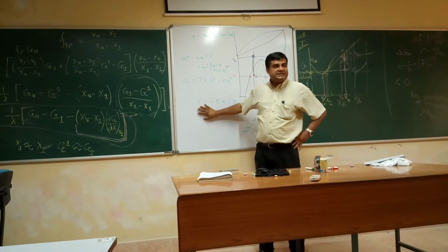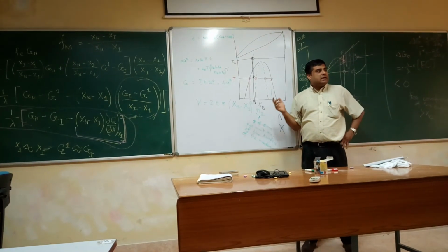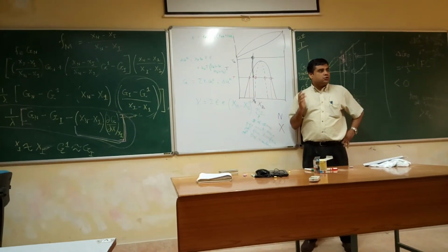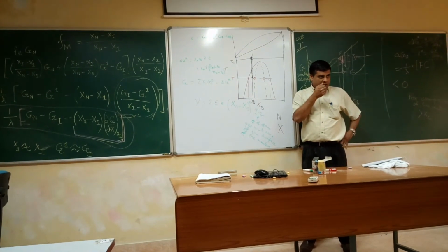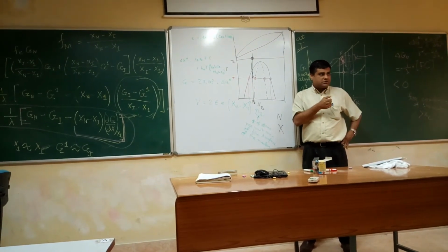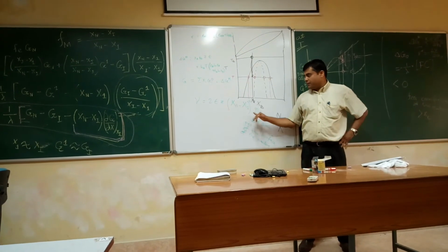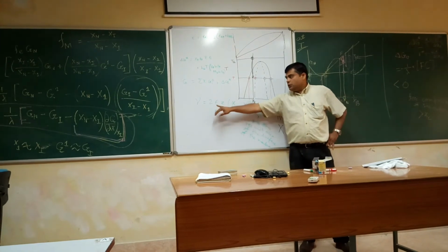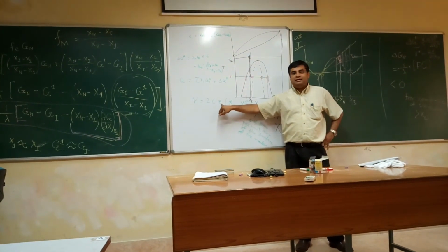And your interfacial energy term, also composition dependent, is proportional to the square of the composition difference between your x beta, that is the nucleus composition, minus the alloy composition. So square of that, multiplied by 2, this interaction parameter epsilon multiplied by z. What is z?